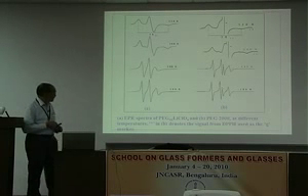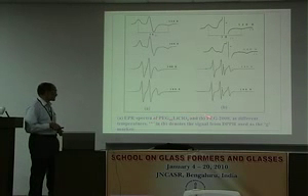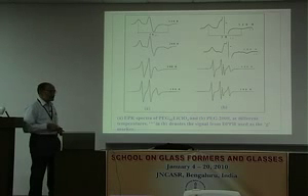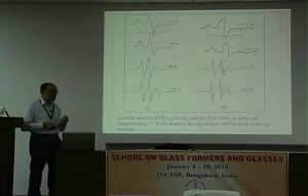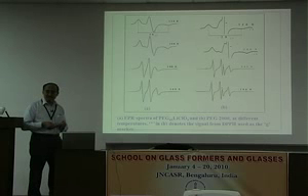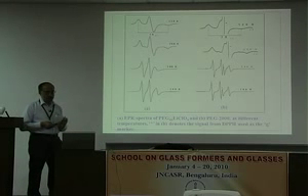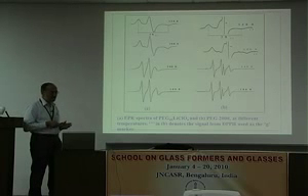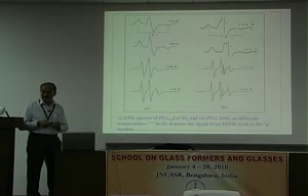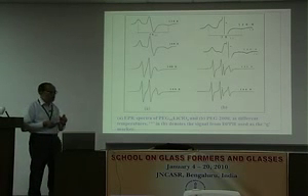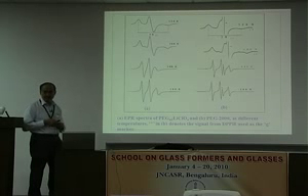Now, we first did the experiment on, like I said, polymers, polyethylene glycol 2000, which does not give any glass transition if you experiment on it using DSC, because it goes into a state where it is partially crystalline and partially glassy, and the change in the specific heat is too small to be detected by the technique of DSC.